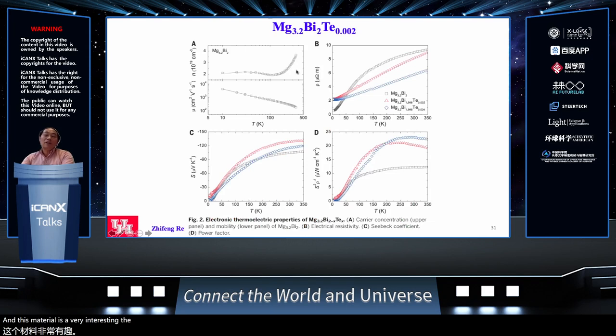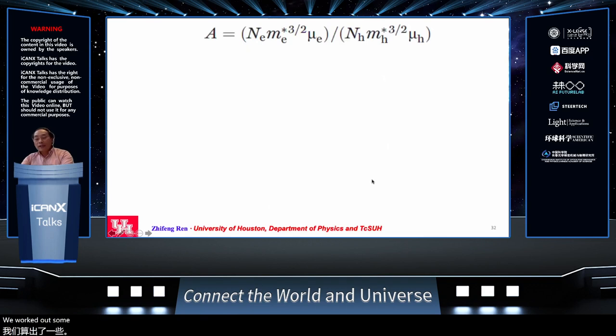The intrinsic material is really a semi-metal because the band gap is very small, and the mobility at room temperature is increased a lot, but not that high. The N-type is not that high. And the resistivity is also improved by a little bit of doping with tellurium, and later on, we worked out some antimony doping.